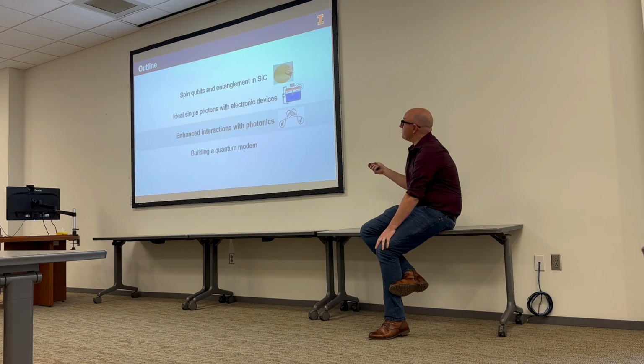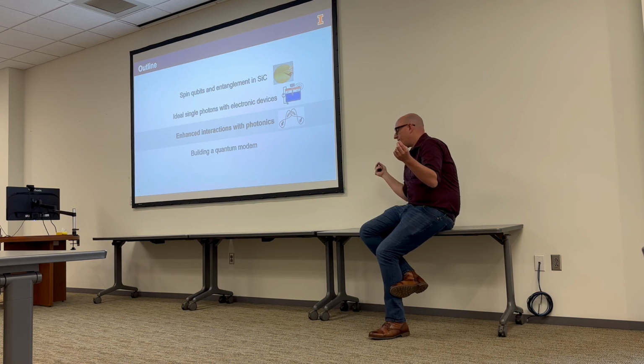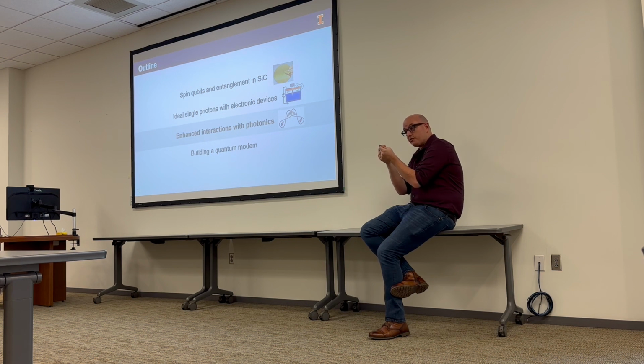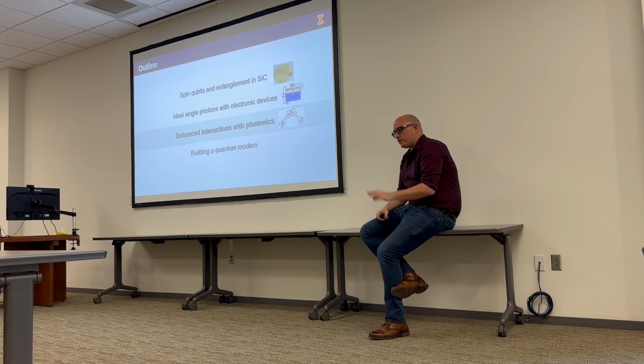In practice, what it does is, I don't have a good figure, but when the photons interfere at the beam splitter, their length determines the coincidence window of this interference dip. Mm-hmm. And so if they become too broad spectrally, too narrow temporally, the detector isn't fast enough to see these time delays. And so there's a technical limit you reach that's around 50 picoseconds. So as long as you're in this nanosecond lifetime regime, you basically never hit that limit, and it doesn't really matter so much. Thanks.